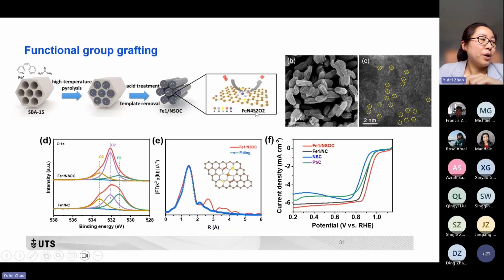Here is the material we have prepared. We have used SBA-15 as a substrate to support these iron single atoms. And we confirmed the material we have achieved by using XPS. It showed the dominant peaks of these epoxy groups. And here is the XAS result to do the simulation. It shows the atomic structure. And also the performance of this material is really good. It showed a half-wave potential of more than 0.9, around 0.92.